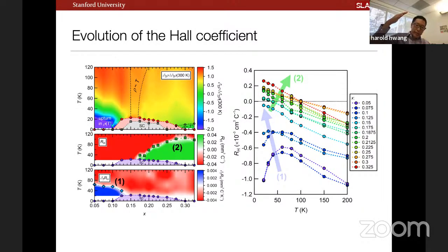the issue is that I might hope to enter a regime of nonlinear Hall coefficient, right? So there are simple games that you can play looking at the magnetoresistance, rho XX and rho XY, to try to pull out these parameters. To all the fields that we've measured, the Hall effect is linear. So it's an under-constrained problem in that regard. So, that's the challenge.